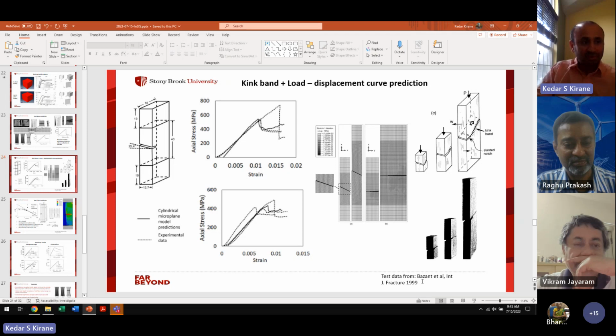So in these experiments they had to have this inclined notch so that the axial splitting didn't happen and then the kink band developed. So yes, it is more challenging than tensile failure for sure. There is first of all the stability problem where you have to make sure the specimen thickness is there. Length also has to be adjusted, otherwise it will overall just buckle. So we have to avoid the overall Euler buckling. And we have these stability issues and isolating the damage mechanism also.